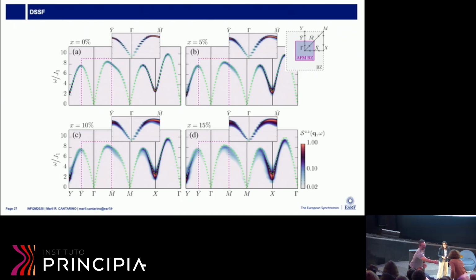I don't know, it's interesting that you ask, because from the point of view of ARPES, I know there are studies on potassium and cobalt doping, and they show, across the whole doping range, effective changes on the electronic structure when you dope. So cobalt and potassium, which are the hole-doped and electron-doped parts of the phase diagram that give rise to superconductivity, show effective changes on the electronic structure. So they would be similar to the case of chromium. But this is not the only necessary ingredient, because something else must be happening to suppress the superconductivity.